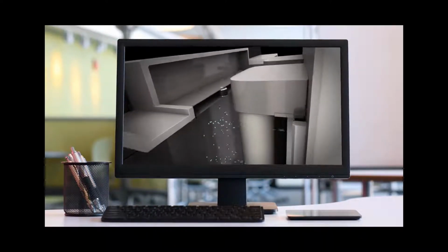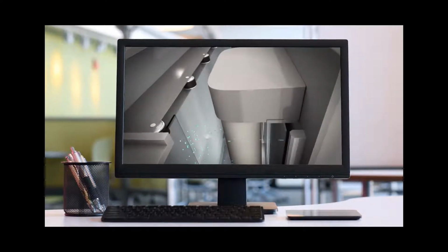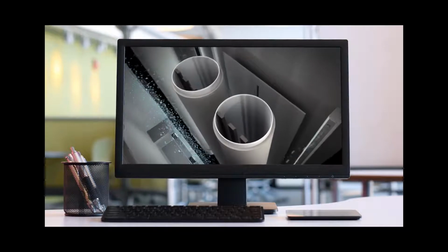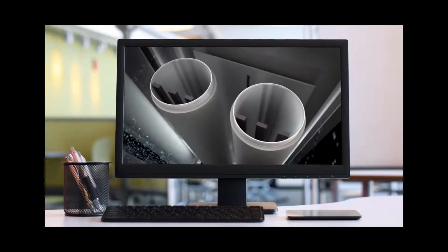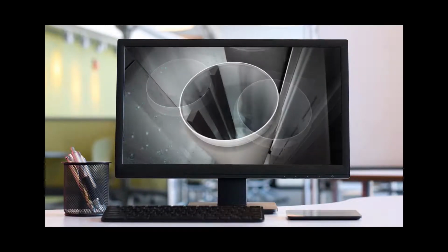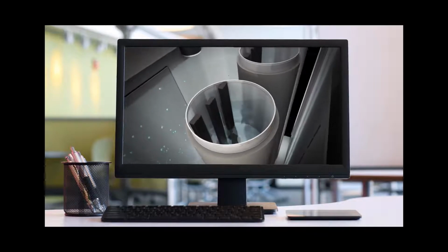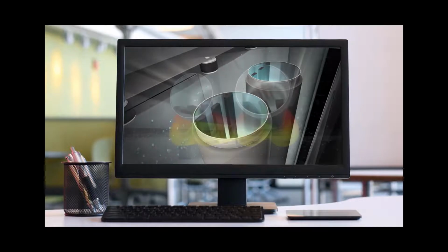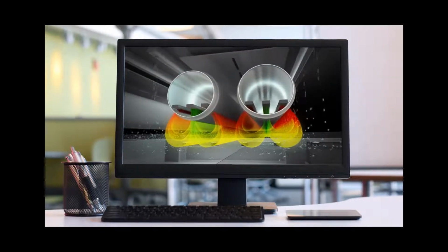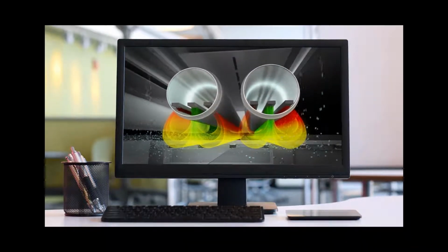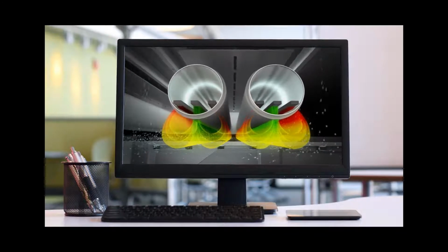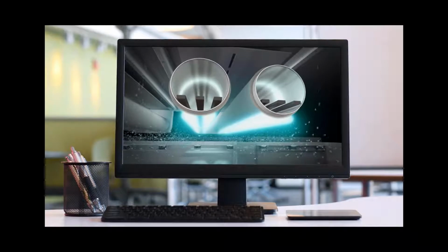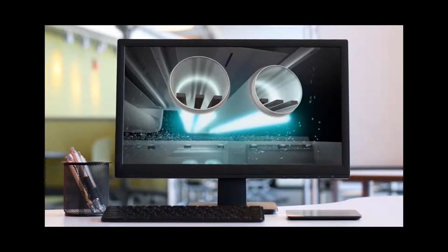Argon gas is introduced continuously to achieve a low-pressure argon atmosphere. A magnet array inside the cylindrical target generates a magnetic field. The target is filled with cooling water, which dissipates the heat generated during the sputtering process. The targets are rotating so that the material is utilized uniformly. A high voltage is applied to the molybdenum target and creates a plasma, which is concentrated along the magnetic field.